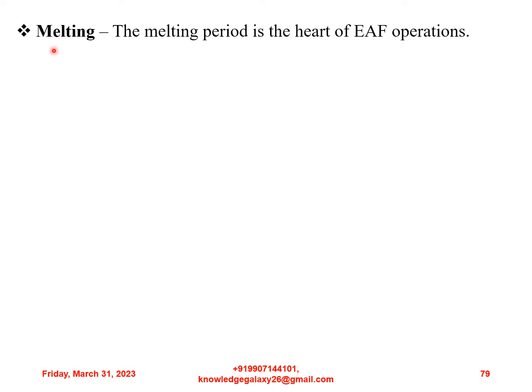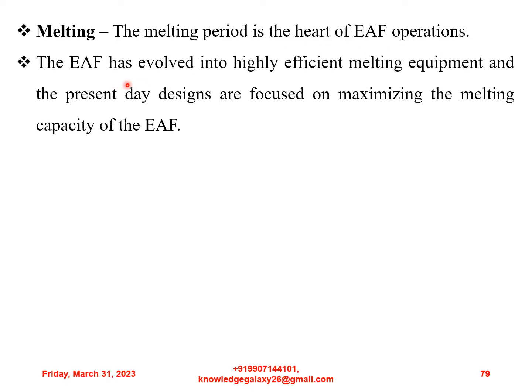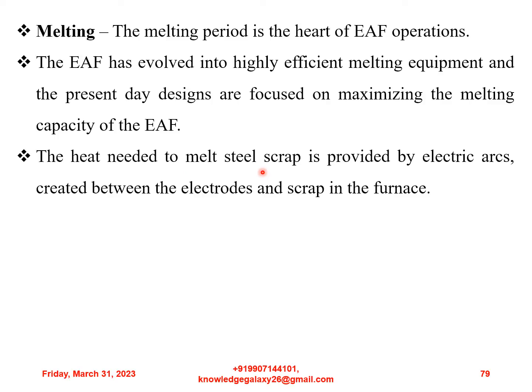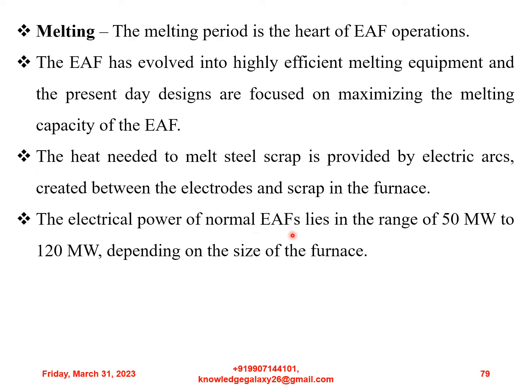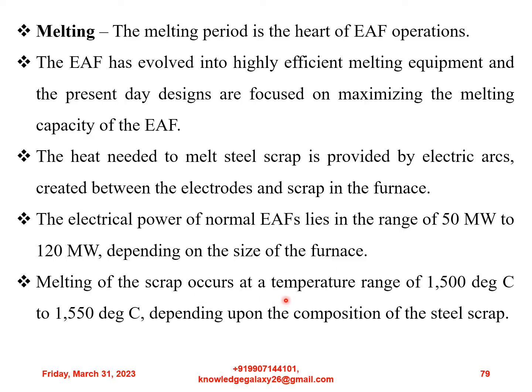Now let us come to the next step, that is melting. The melting period is the heart of electric arc furnace operations. The electric arc furnace has evolved into highly efficient melting equipment and the present day designs are focused on maximizing the melting capacity of the electric arc furnaces. The heat needed to melt steel scrap is provided by electric arcs created between the electrodes and the scrap in the furnace. The electrical power of normal electric arc furnaces lies in the range of 50 megawatt to 120 megawatt depending on the size of the furnace. Melting of the scrap occurs at a temperature range of 1500 degrees Celsius to 1550 degrees Celsius depending upon the composition of the steel scrap.